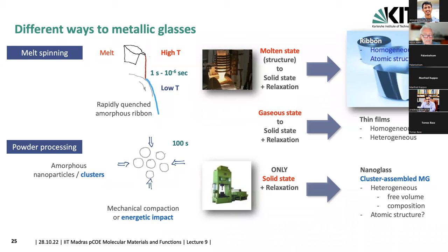Typically, metallic glasses are prepared in alloy systems of 2, 3 to 5 different elements, and they're rapidly quenched from the molten state. Then you do some solid state relaxation, and you get a homogeneous atomic structure. The elements are homogeneously distributed in the sample. But you always go from a high temperature to a low temperature in very short time here, 10 to the minus 6 seconds. And if you have more complex alloy composition, you can slow the cooling in order to get still an amorphous material.